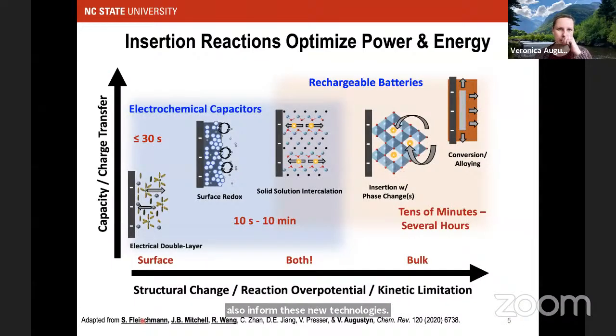So if we think back to energy storage, why are insertion reactions so special? To me, the key thing is that they really optimize power and energy in the ultimate device. And on the materials level, what we mean is that they're optimizing the capacity or the degree of charge transfer that can occur with the kinetics limitations that can take place. And so this is kind of a landscape of different kinds of energy storage processes that can occur on electrode materials. The fastest processes, but the ones that yield the lowest capacities, are those associated with electric double layer formation, where there's only electrostatic interactions taking place, no charge transfer, very fast, a lot of cyclability, very little structural change in the materials, but we don't store a lot of charge.